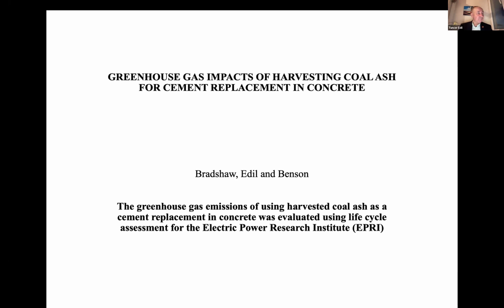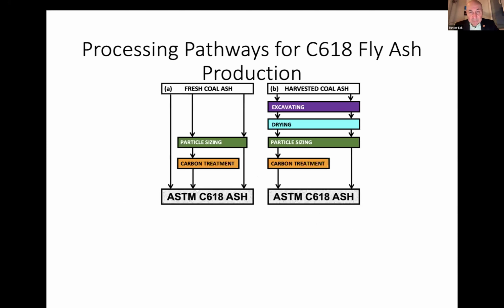And so for those reasons, people like to use different percentages of fly ash, 20, 30, 40% sometimes. And it gives you a different strength concrete. So we evaluated the effect of fly ash in beneficial use in concrete years ago. But now the Electric Power Research Institute asked us to evaluate and compare the harvested coal ash in these terms. Processing pathways for generating a C618 fly ash. This is the ASTM designation for the fly ash. And if you have that fly ash, you can mix it with Portland cement in concrete production.